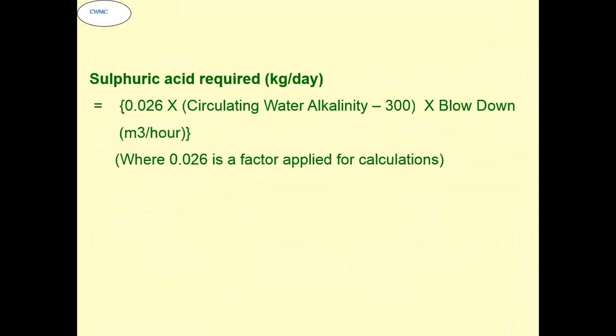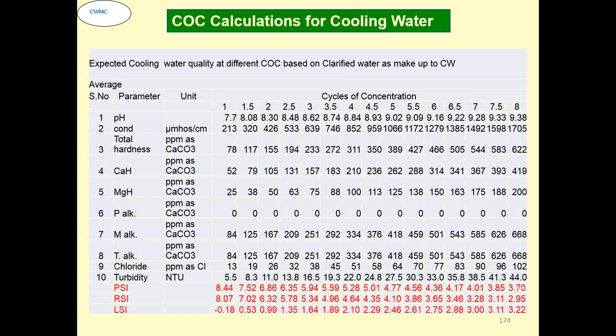Normally the pH is controlled at a certain level. To control the pH, what we do is we use sulfuric acid. This is the formula that we can use for calculating the sulfuric acid that is required per day in terms of kg per day. Simply it is 0.026 multiplied by the circulating water alkalinity minus the alkalinity that we want to maintain. I have put 300 figure here, but whatever the alkalinity that we want to maintain, that I have to put there. So whatever the delta alkalinity that comes there multiplied by blowdown in terms of meter cube per hour will give you sulfuric acid kg per day that is required.